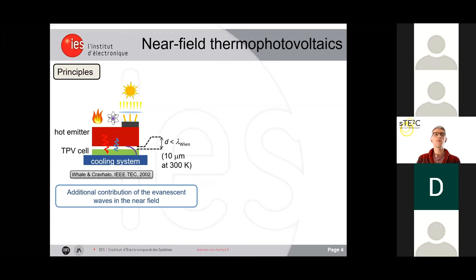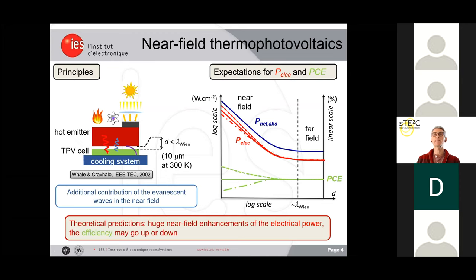And then, thanks to the additional contribution of the evanescent waves in the near field, what we will expect is that the radiation power, which is constant in the far field, you see that on the graph on the right, will increase thanks to these evanescent waves. Now, for the electrical power, if the increase follows the same trend, then the efficiency will remain the same in the near field. However, if the increase of the electrical power in the near field is larger, then efficiency will increase. And if the rate is smaller, efficiency will decrease. But in any case, there is a huge near field enhancement of the electrical power.